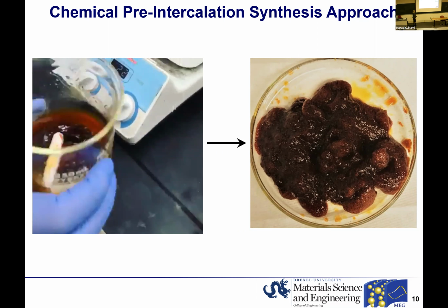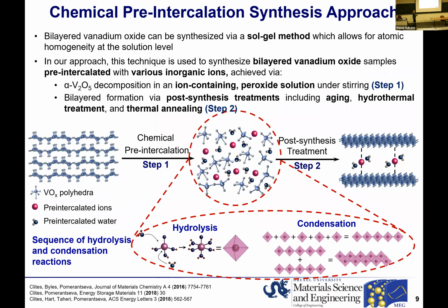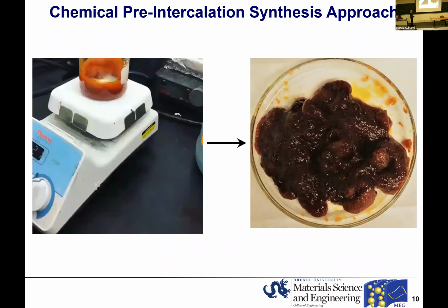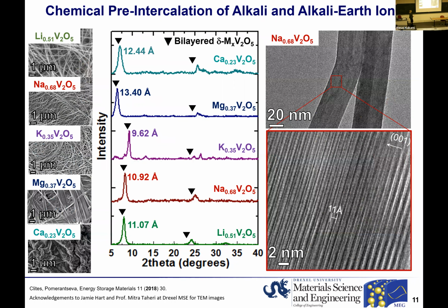However, after this step, we can also use this raspberry jam for post-synthesis treatment, and this can include either hydrothermal treatment or annealing at elevated temperatures. And that gives us another degree of control of the structure and chemical composition of the final product material. And here is what we have synthesized utilizing different inorganic ions: lithium, sodium, potassium, magnesium, and calcium. And with the alpha V2O5 precursor, all materials have one-dimensional nanobelt morphology.